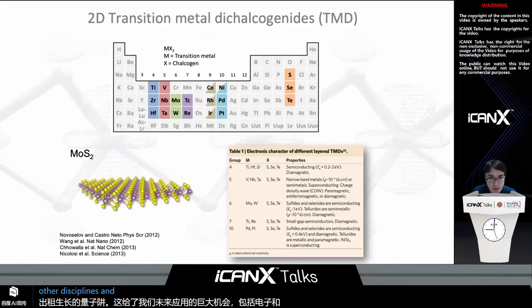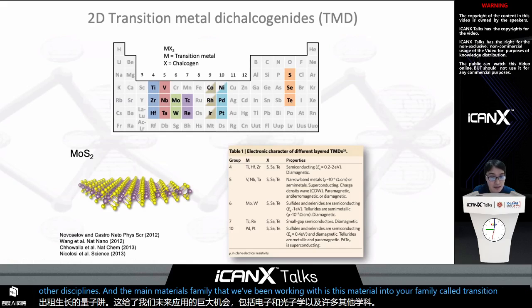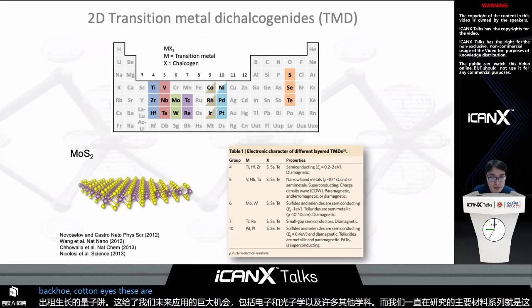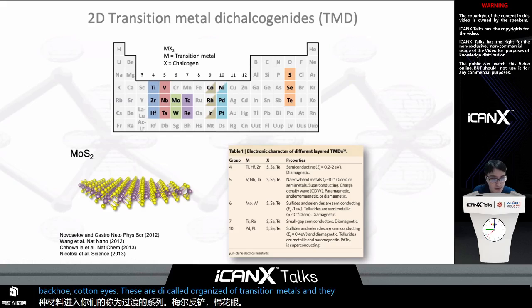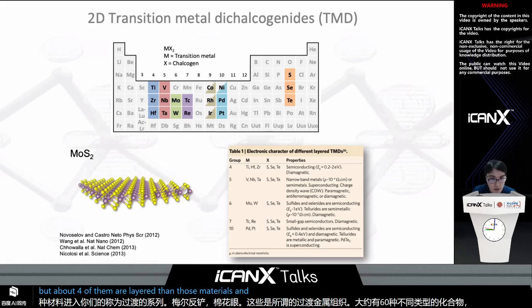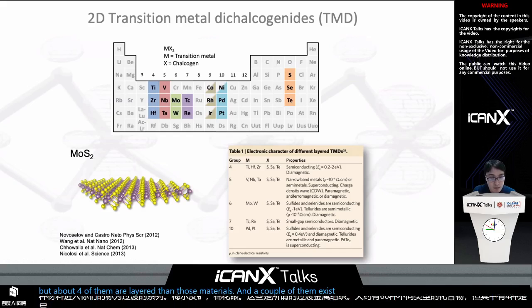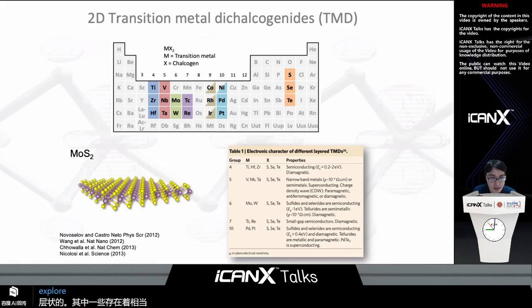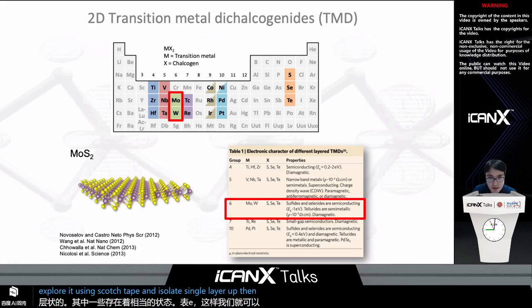And the main materials family that we've been working with is called transition metal dichalcogenides. These are dichalcogenides of transition metals, and there are about 60 different types of these compounds, but about 40 of them are layered van der Waals materials, and a couple of them exist fairly stably, such that we can simply exfoliate using Scotch tape and isolate a single layer of them. Especially the group 6 ones are semiconductors, and they happen to have a direct band gap, so they are very attractive for optoelectronics applications.